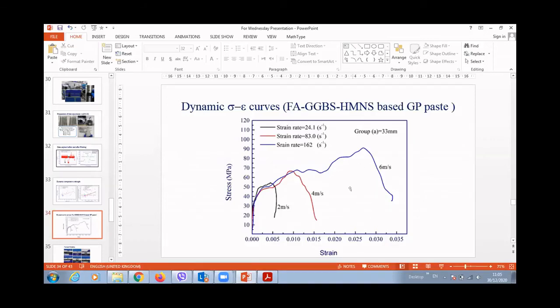So this is an example for a group of 33 millimeters at different impact speeds. At the first stage, we found that the curve has very similar variation patterns, in which the stress first increased almost linearly with the strain, and this represents the elastic relationship between stress and strain. Then